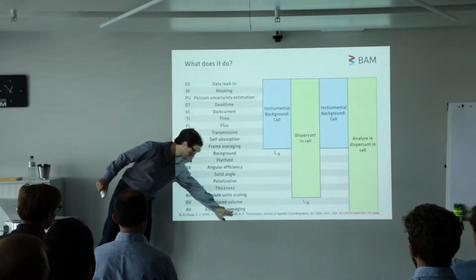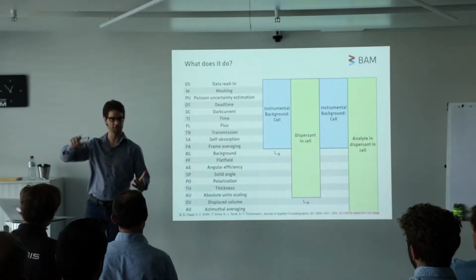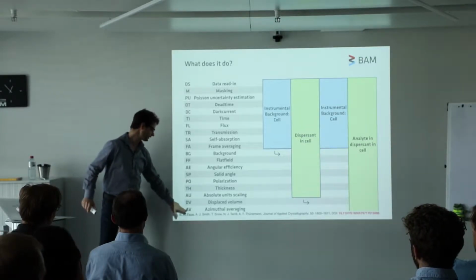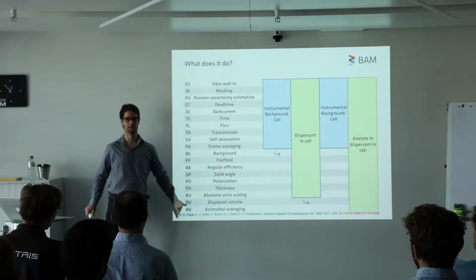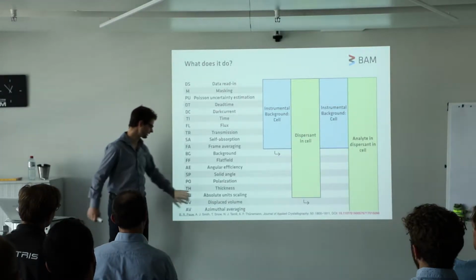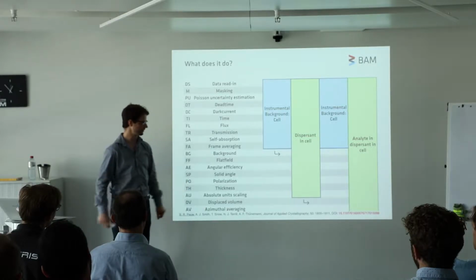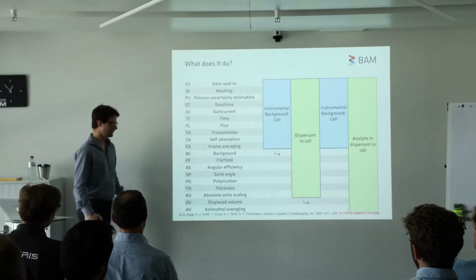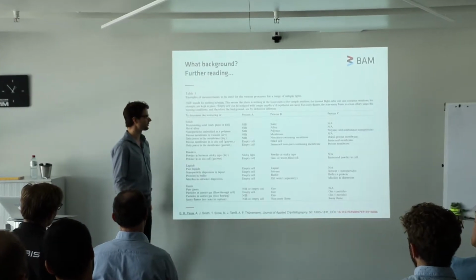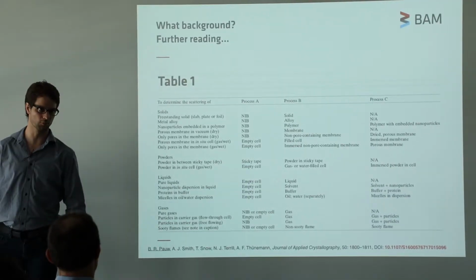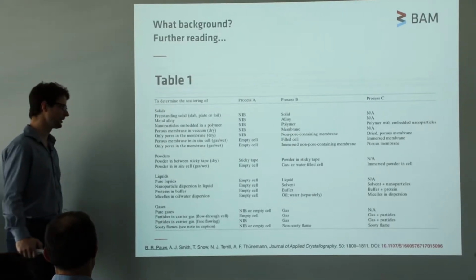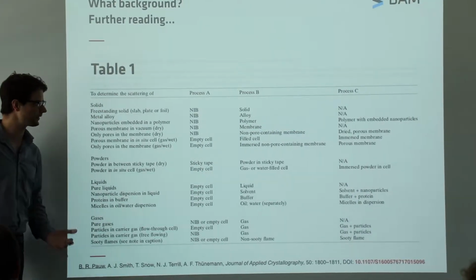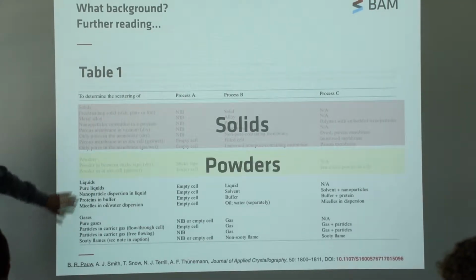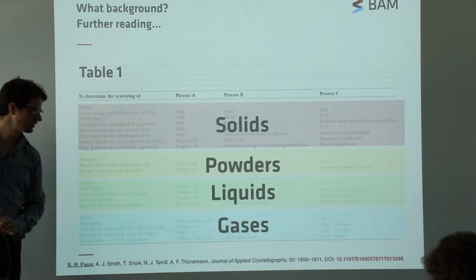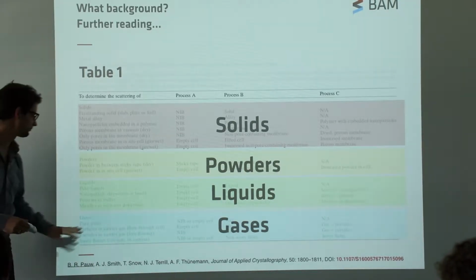Note that the azimuthal averaging, what brings it into a one-dimensional curve, is optional. So if you have 2-dimensional data, you stop here. And then you have your 2-dimensional data in, as I said, as good as it gets. Now this is just 2 examples. We have in our paper, in table 1, a list where we clarify what background you need to measure for all of these samples. In case you're measuring solid dispersions, powders, liquids, and gases. We're not doing plasmas just yet, but that should be pretty close, maybe.